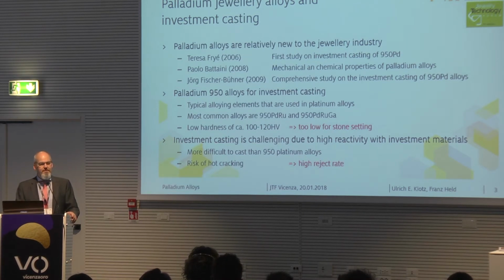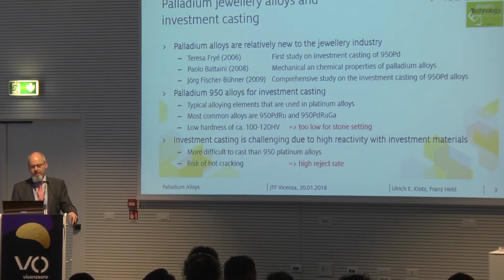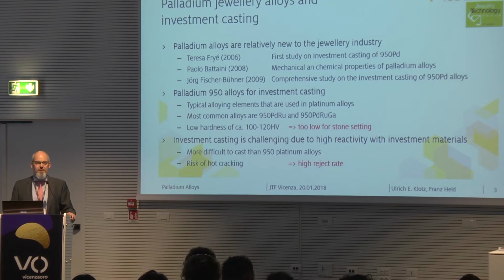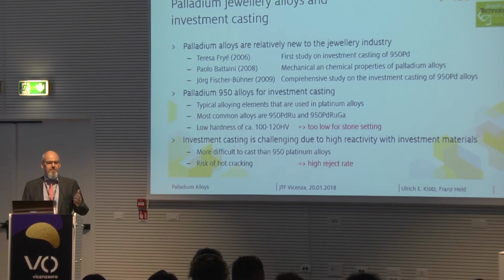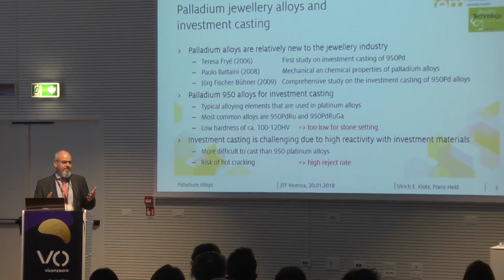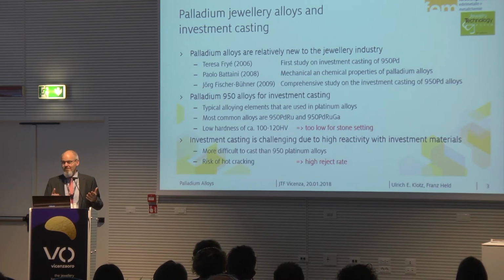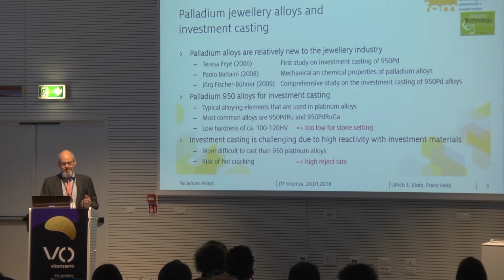And therefore there's always a risk of bending and distortion of such jewelry. But another issue is the production point. Palladium is even more difficult to cast than platinum because it's even more reactive than platinum. And so you get the risk of porosity, as we heard this morning, shrinkage porosity or gas porosity in particular. And there's also a risk of hot cracking. This in general leads to quite high production costs, which might be even higher than for platinum, but at the same time the price of palladium was lower than for platinum, and of course the renommee of the alloy is not as high as for platinum.